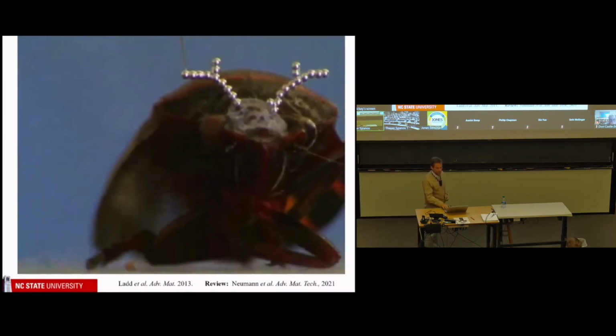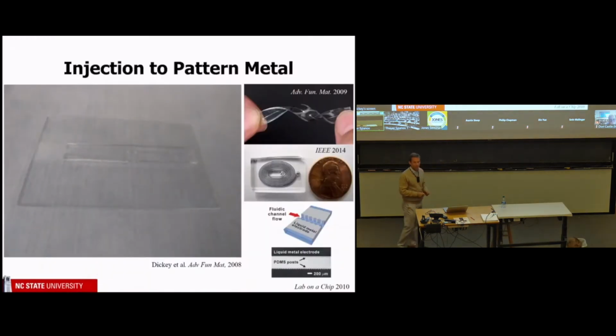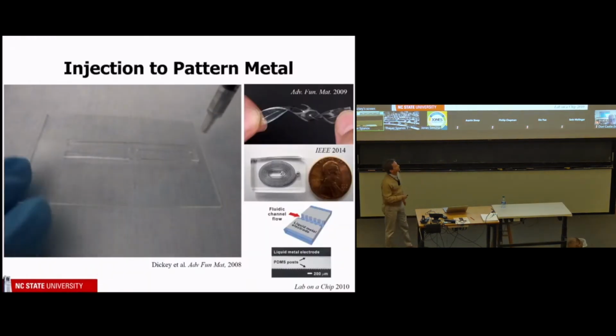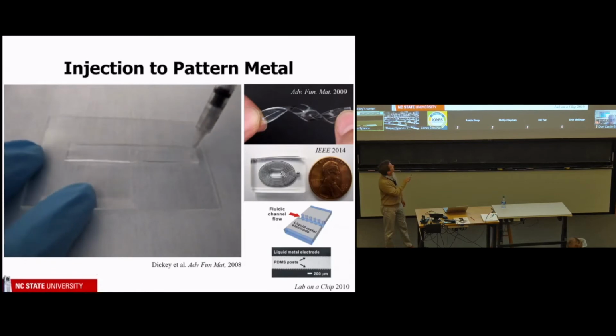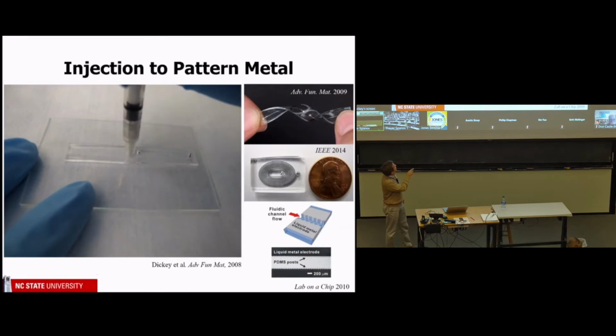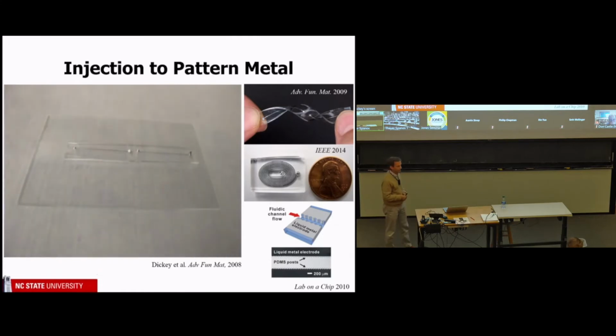So this is one way you can pattern it. You can also pattern it by injection. Now, obviously, you couldn't do this with aluminum or copper, at least not in an easy way. So this is what we call a microfluidic channel. It's just a tube. There's an outlet hole right here. We use our thumb that breaks the oxide very easily, and the low viscosity allows it to flow in. Going to do it again from here to here. You'll see it flow through and pop up on the other side. So this is kind of an interesting way to pattern metals at room temperature just by injecting them.